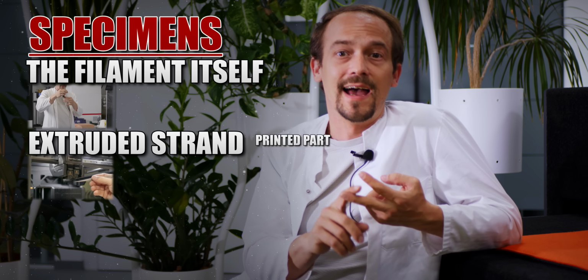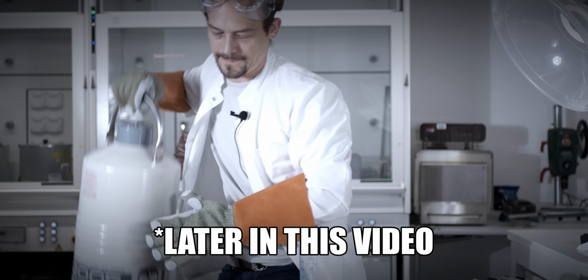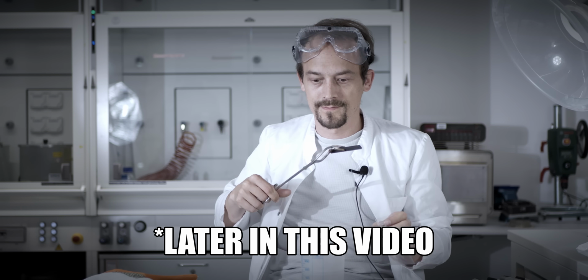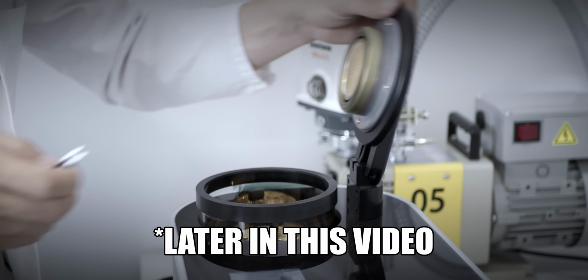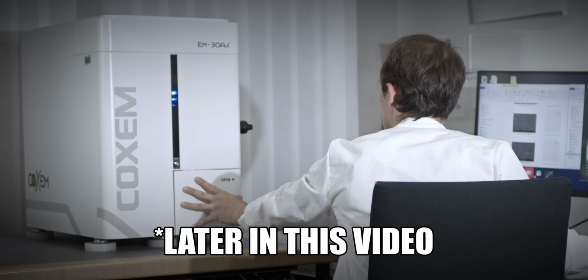To figure this out, we're going to look at 3 stages of the material: the filament itself, an extruded strand, and a printed part. We cut cross-sections through the layer and see how the fiber distribution is. But here's the fun part. To get a clean cut through the part, we're going to freeze it in liquid nitrogen to avoid layer smearing while breaking. Then we're going to gold plate it using sputter plating with plasma, and put it into a scanning electron microscope. Don't worry, I will explain how all of that works later.